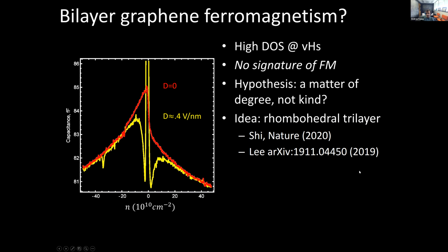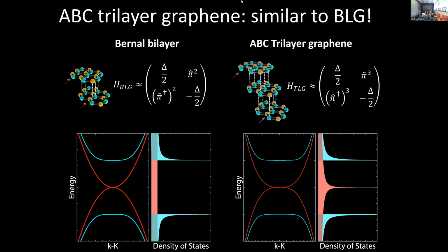by a few works that started to see signatures, let's say, of correlated electron physics in rhombohedral graphite of various types. Okay, and so you can see this by looking at the simplest, a two-band model for the low energy physics near the charge neutrality point in bilayer graphene and ABC trilayer graphene.